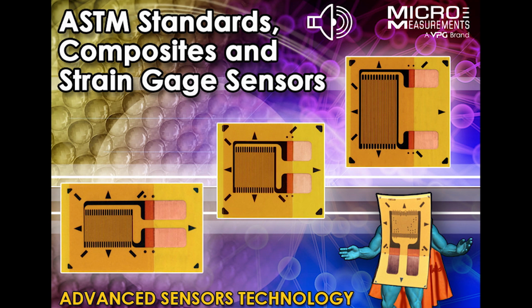And also, it's very important when, let's say, you do an edgewise test, like a C364, where you're going to basically put the material on its side. You're going to be pushing down on the two skins and the core. But the material, let's say it's a 4x4 size specimen, it's only 1/2 inch thick. There's a lot of buckling that could happen there. And not having gauges on that coupon, you might either underestimate or overestimate the modulus, depending on whether you're on the tension side or the compressive side, if the skins are debonding from the core. So these are tests where strain gauges are not only valuable, they're necessary.